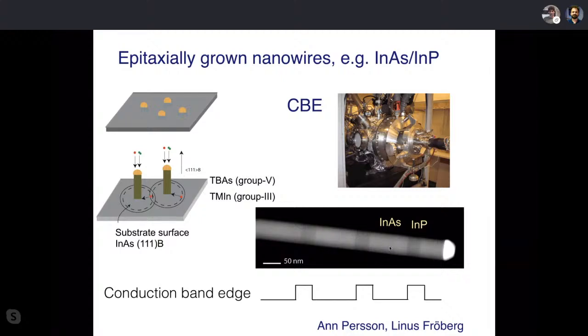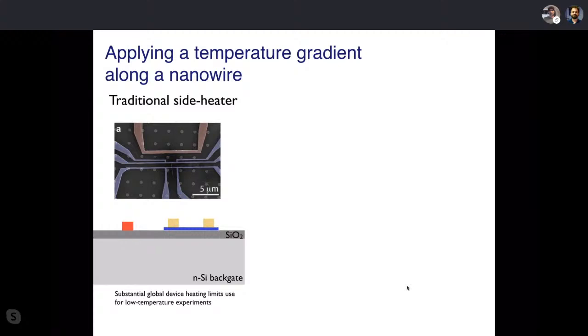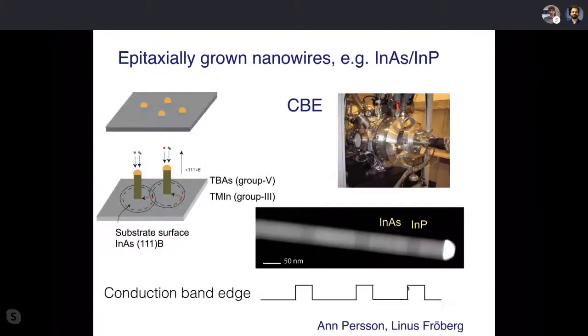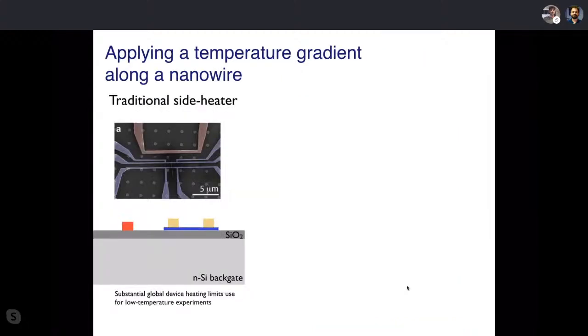So here's a system that was developed in the early part of the 2000s. In this case, it's 3 energy barriers. Indium arsenide is a system with a small band gap. Indium phosphide is a material with a big band gap. The CBE technique allows you to make very sharp interfaces between the two materials, really sort of atomic layers, which gives you very sharp bumps in the conduction band. And you can see that you can build a quantum dot out of this. So I'll show this to you in a moment. So this is one ingredient. This was developed to perfection in the last 10 years or so, I would say, or maybe a bit more.